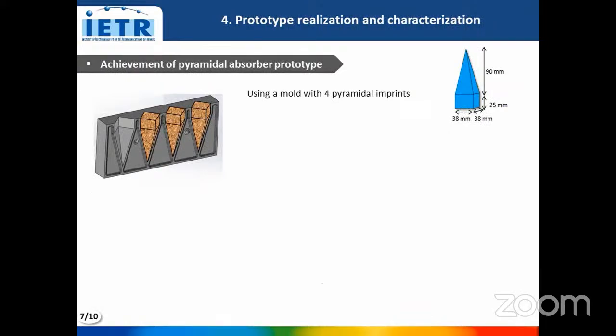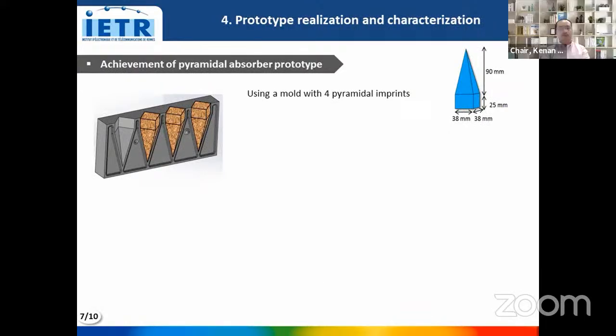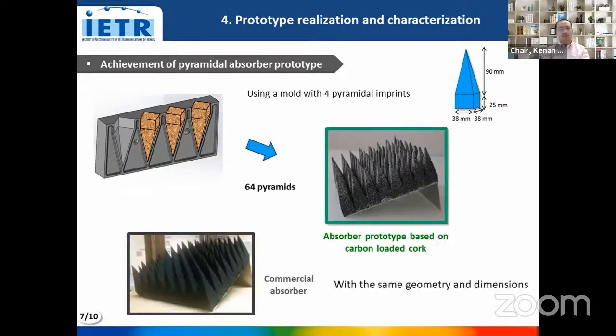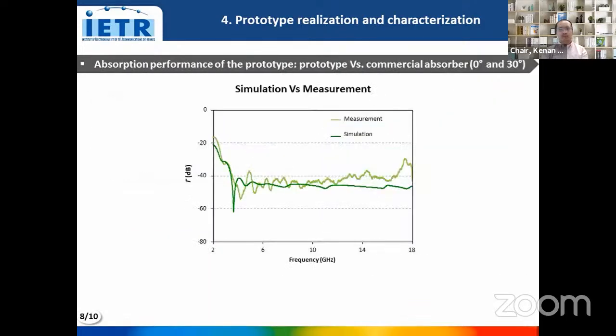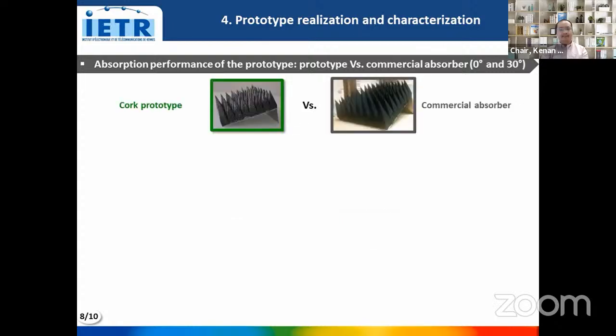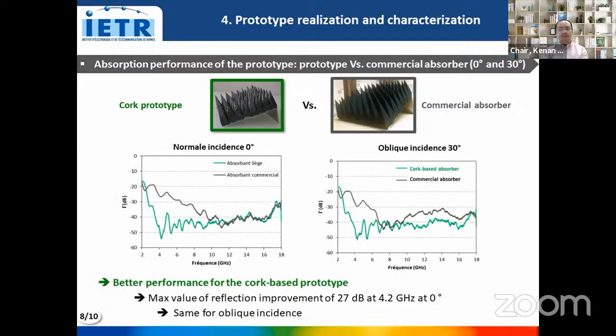A pyramidal absorber prototype was then realized with this composition and with 64 pyramids. This prototype has a similar dimension to the commercial absorber shown here in this photo. Here is the measurement of our prototype compared to its simulation, and we can observe a good concordance between these results. Now, the measurement of this prototype is compared to the commercial one for normal and oblique incidence of electromagnetic waves. We can see here that we obtain a better performance for our prototype than the commercial one, especially at low frequencies. The improvement is up to 27 dB.